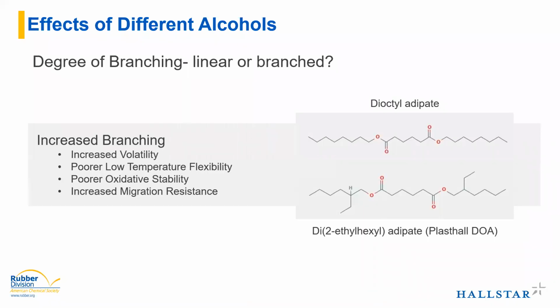And the other thing to consider is branching. Branching can give some interesting effects on your material when you're processing. The examples shown here, technically on top is dioctyl adipate, which is actually not DOA, which most people see. Most people say DOA and say dioctyl, but what they really mean is this di-2-ethylhexyl adipate. 2-ethylhexyl alcohol is much less expensive than just octyl alcohol, the straight chain, so it's much more commonly used, but instead of using the full name with the 2EH there, a lot of people say DO instead.